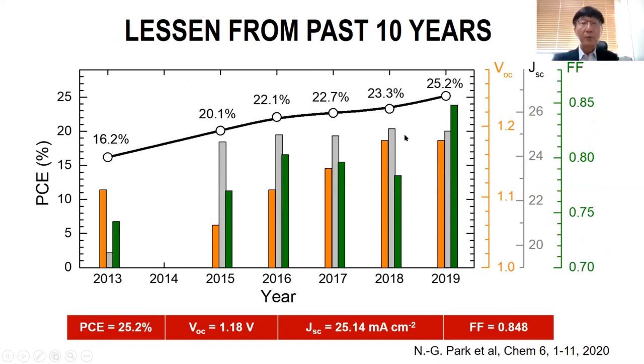past 10 years. For instance, the certified efficiency went from 16.2% to 25.2%, which we achieved last year. And actually, there is no significant increase in short circuit photocurrent density. However, there was a large increase in the open circuit voltage, and from 23.3% going up to 25.2%, the additional increase was achieved, for instance, by a large increase in the fill factor. So a 25.2% efficiency cell has 1.18 volt and 25 milliamps per square centimeter, and the fill factor is crossing 0.85.